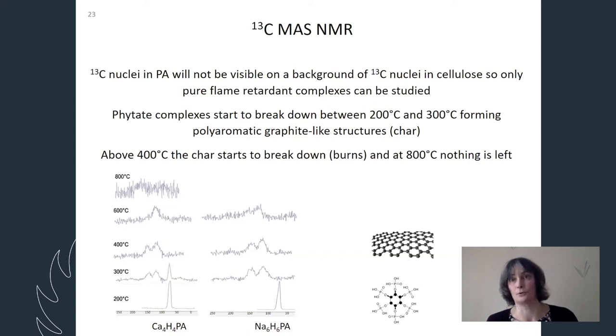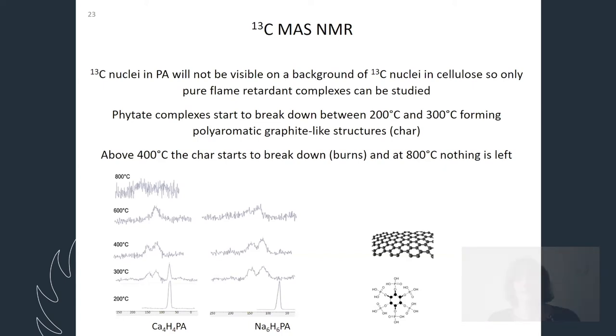Here we have only the pure complexes, so we don't have any cellulose, only the phytate. But the phosphate groups are gone, and then those carbon rings, they start to fuse together to form a graphite-like aromatic, polyaromatic char. And when we increase the temperature even more, we see that the signals become weaker, we have more noise. That means that this char disappears, it slowly starts to combust, and at 800 degrees there is nothing left of this carbon part.